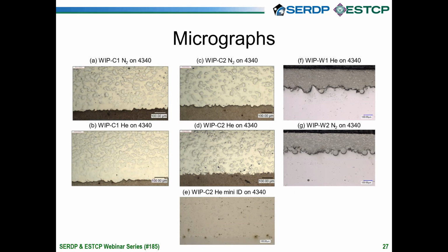Another interesting thing to point out about these micrographs is the difference between the methods of combination. So remember, the C1 and C2 feedstocks are produced by blending, while the W1 and W2 feedstocks are produced by spray drying and sintering. And you can see that in the microstructure. So with the C1 and C2 micrographs, you can actually see what were once the hard phase particles that are now embedded in a soft phase matrix.